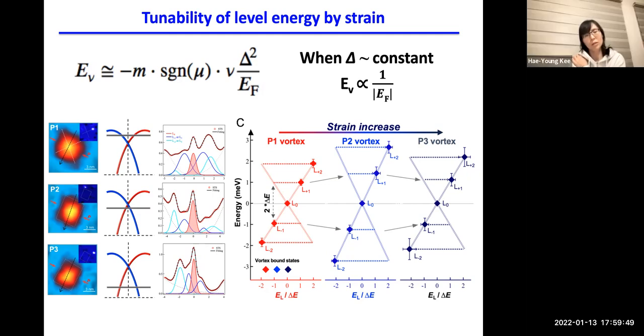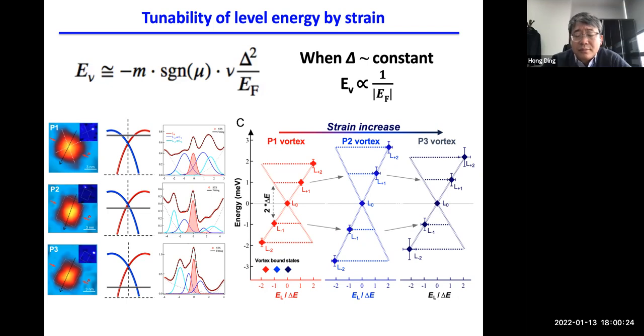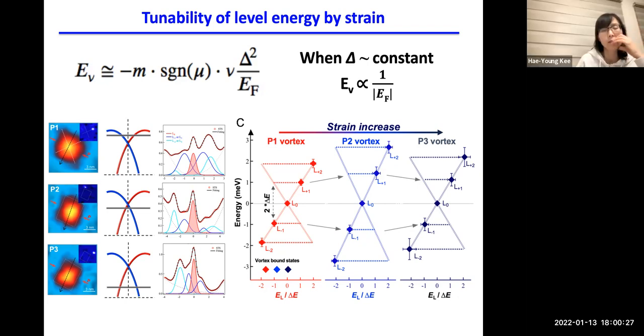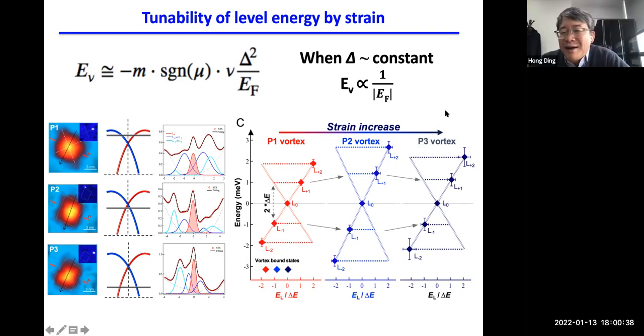So I have a question as well. If I understand from the Kane and Fu papers and what you are doing, what you need is the band inversion that generates a TI effect, and then the EF has to be in the right place. So does iron have to be special in that sense? Because I can find superconductors with t2g orbitals where, in principle, band inversion might occur somewhere, right? So it may not be that iron is special, it happens to be the case, but in principle we can find more abundant superconductors. Is that right? Yeah, absolutely. You are absolutely correct.